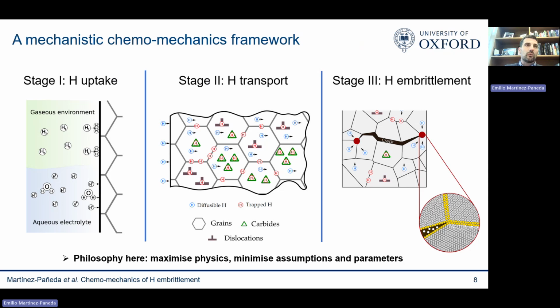The only way to do that is by trying to resolve the physics of your problem explicitly, directly. So I'll explain how our modeling framework encompasses the three main stages of hydrogen embrittlement: the hydrogen ingress part, the uptake of hydrogen into the metal; the transport of hydrogen within the material; and finally the embrittlement process itself, how hydrogen assists in nucleating and growing cracks. Let me go one by one.